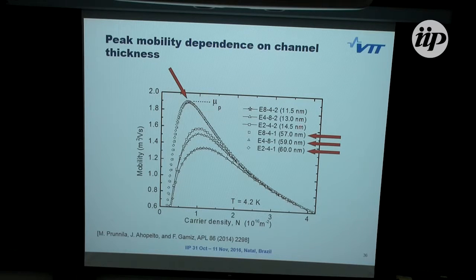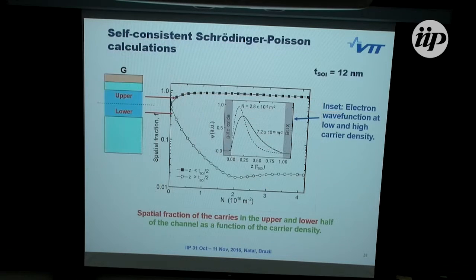So at this stage, there's no effect of the channel thickness. At 14 nanometer thick channel, the peak mobility drops. At 13, it drops more, and at 11, it drops even more. And this is rather easy to understand. So there's a Schrodinger-Poisson calculation of the system. This is the channel, and in this case it is a 12 nanometer thick channel.